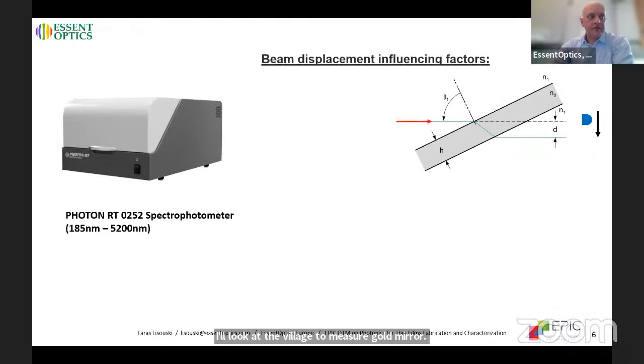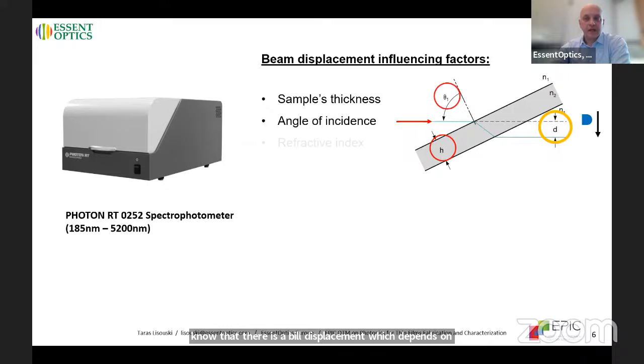We take very precise attention and care to routine, typical daily measurements of samples, which fortunately are not taken care of by other companies. Take, for example, a case of transmission measurement of a sample at a specific angle of incidence. Obviously, you know that there is a beam displacement, which depends on three factors: sample thickness, angle of incidence, and index. So the beam is displaced, and no other system is capable of tracking this beam.